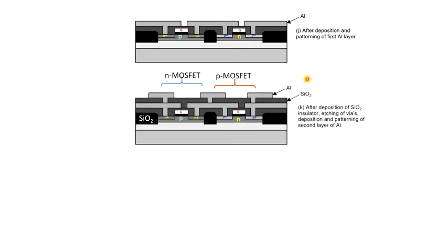So you can see it here. This is metal line 1, right? And then we have deposited one more silicon dioxide layer, and then created these vias, and then deposited another metal and patterned it. By saying vias, what we mean is that we deposit any dielectric, do a dry etch, and open a passage through this dielectric. That is called a via in simple terms. Okay, I hope this is clear to you. If there is metal line 3, then it will be above, and again one more silicon dioxide layer and then metal line, connected via vias.